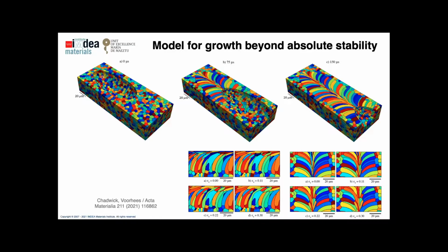We will have full solute trapping no matter what. So they don't even consider the solute field because of complete solute trapping, K equals 1. So in the end, you can have a phase field model that gives you a trace of the thermal history to some extent, and you can start playing with things like the anisotropy of your kinetic coefficient with such a model. But you will not have the dendritic structure that you want to see inside.